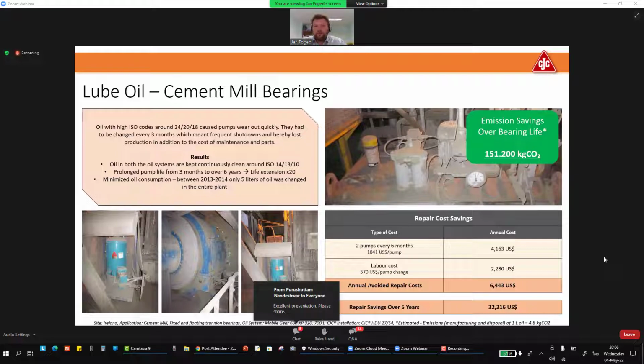And of course, you don't have to change the oil. Again, most of the oil in cement factories is in chemically perfectly good condition, but just contaminated. So a lot of oil changes are simply because of contamination, not because of the chemical condition of the oil. And to give you an idea of the emission savings on just this alone, based on oil produced, you have an emission saving of 151,200, which is always, of course, great to show to your green books. But also, and probably where most people are looking at money, if you look at the lifetime and the cost of the pump, you see down below, the savings over the 5 years was over $32,000.